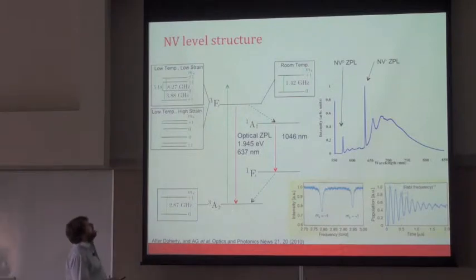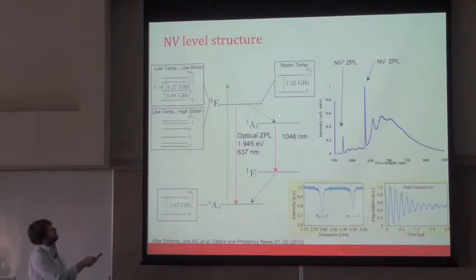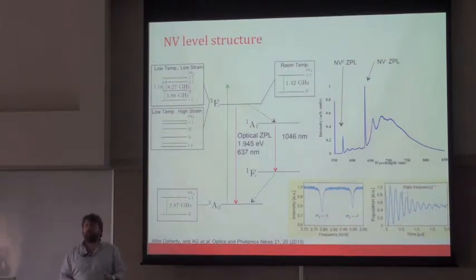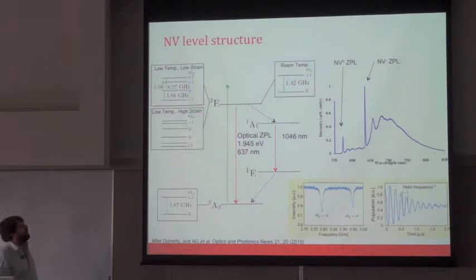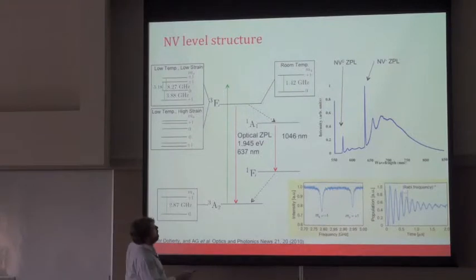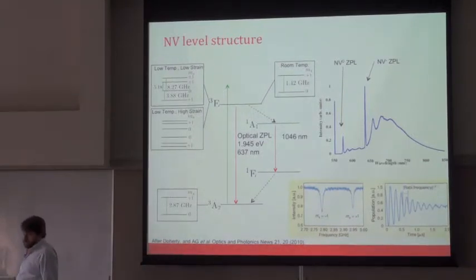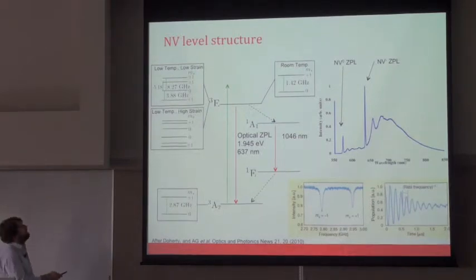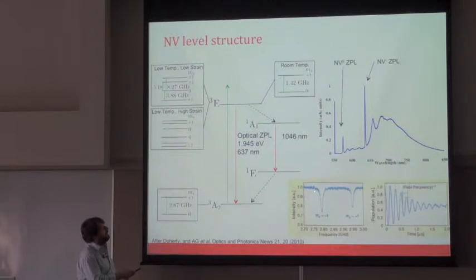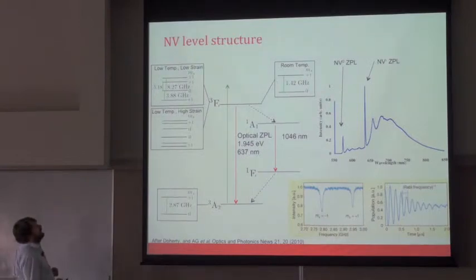Which means that in an ideal case, when you pump with a green laser here, you will optically pump your NV centers into this spin zero ground state. If you were in the plus minus one state, because you see this transition, the brightness from the spin plus minus one states is slightly less, so this gives you a direct optical readout of an individual electron spin, which you can then use to do individual nuclear spin readout as well. It's not perfect. I've described this as if it were a perfect spin conserving or spin non-conserving transition. In fact, it isn't. There are finite branching ratios, and so the visibility of the fringes here is not ideal, but it's certainly enough to do single center spin readout.